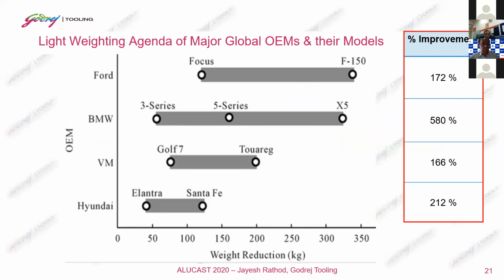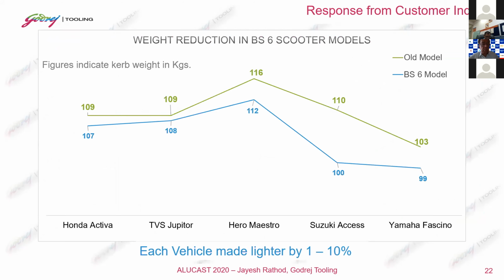we can see how each auto OEM has responded to the requirement of weight reduction. The initial saving of 50 to 100 kg per vehicle has now been targeted at 200 to 325 kg. So that is an improvement in the range of 172% to 580%. These are very aggressive weight reduction programs being pursued by auto OEMs.